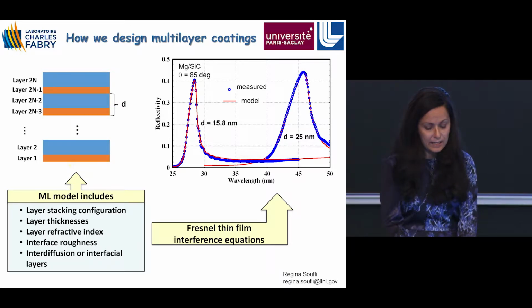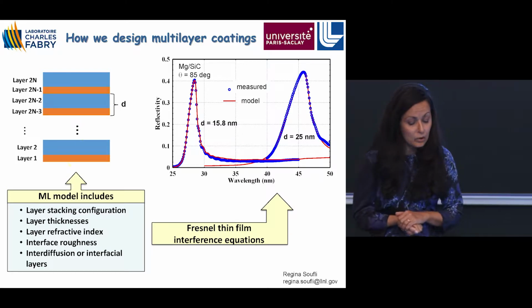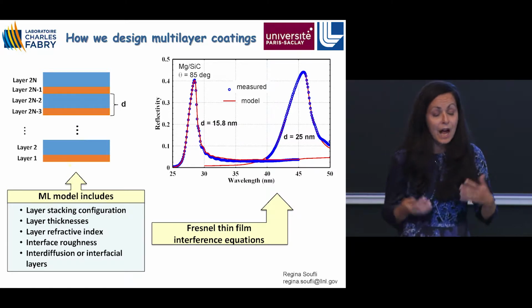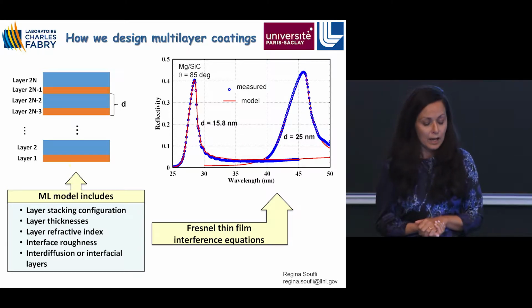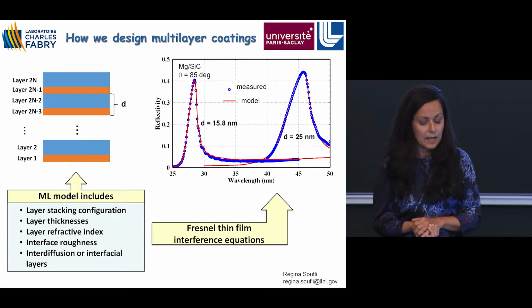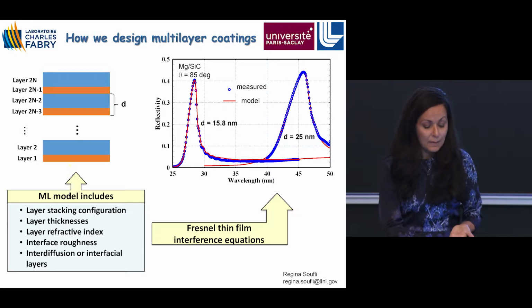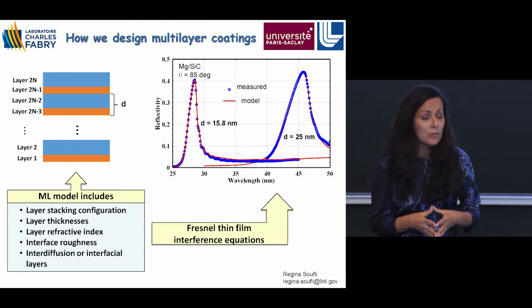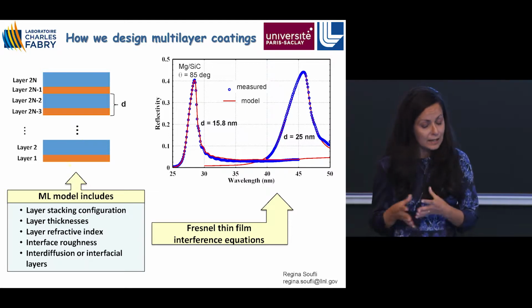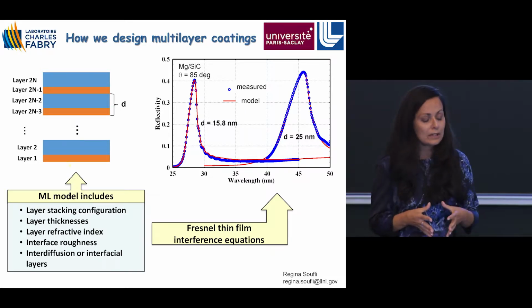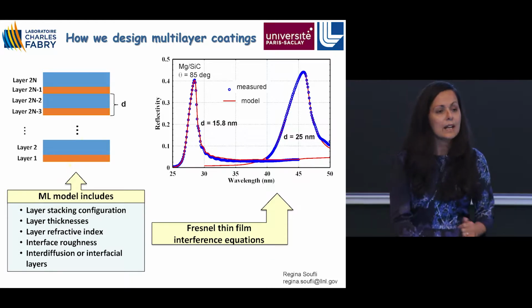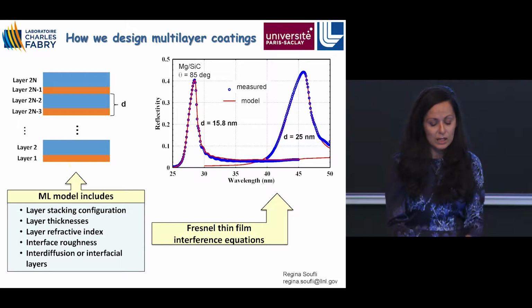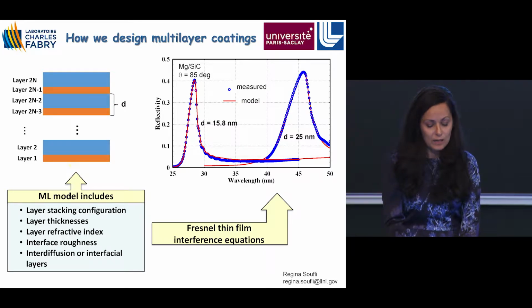The refractive index, the interfacial roughness, and the interdiffusion between the layers are not well known for short wavelength materials. And these are very important parameters for the model. Furthermore, they cannot be determined theoretically, as I'm going to explain. You need to determine them experimentally. And so this is why it is challenging to make these coatings, because these very important parameters here are not well known.